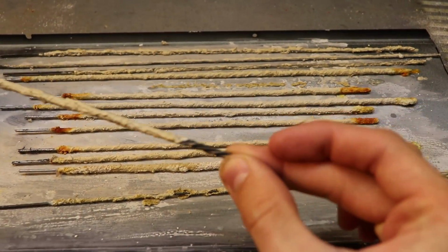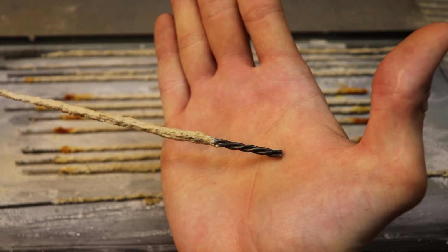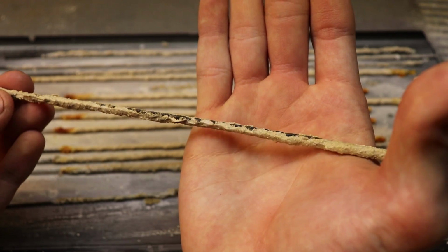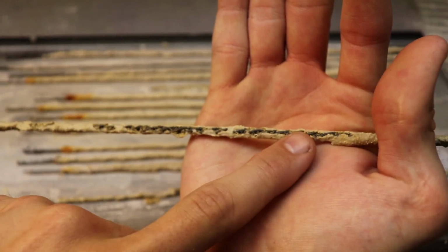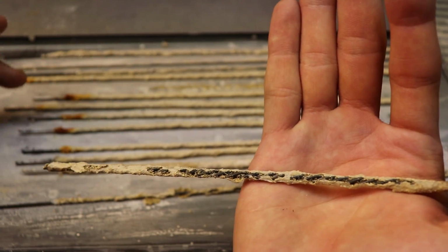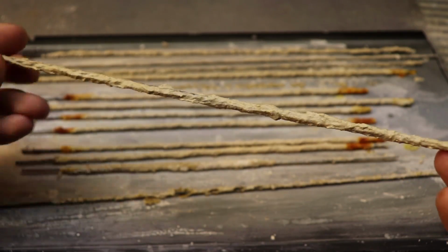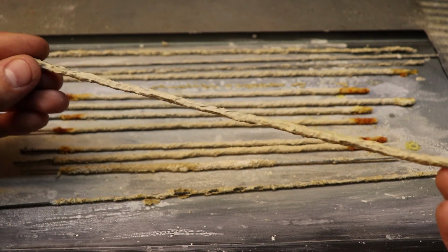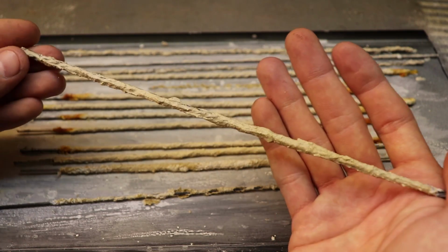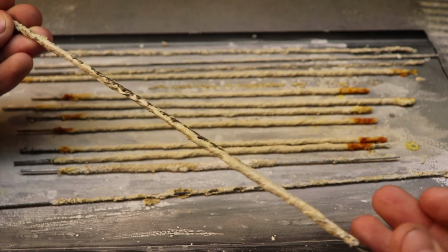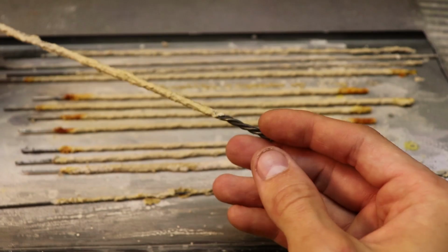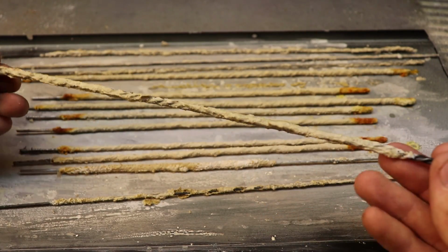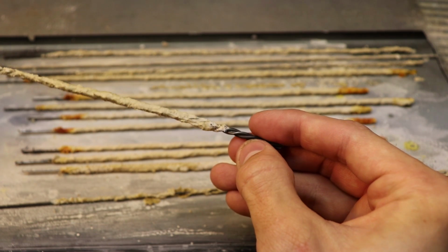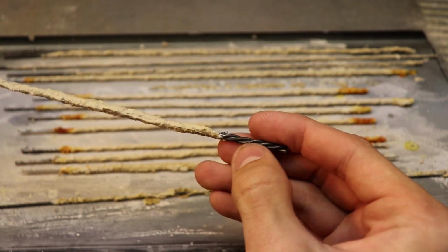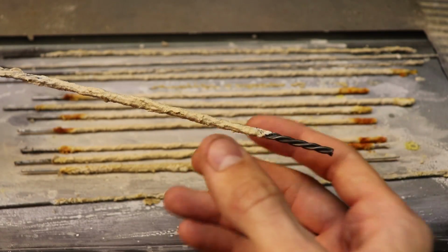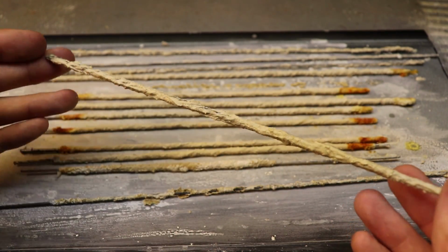Here, I'll try my autofocus, but as you can see, I wrapped 3 wires together and I didn't use any paper. And of course, when I dried out the rod, some of the solution stuck onto the metal sheet itself, and that's why it came off. But overall, you can see on the other side, it is pretty uniform. The coverage is pretty uniform on this rod. And it makes me think that if you twist maybe not necessarily 3 wires, but 2 wires together, that might be enough to give you a certain trench, as you can see, in between the wires to hold the solution there and hold it in place for it to dry out.